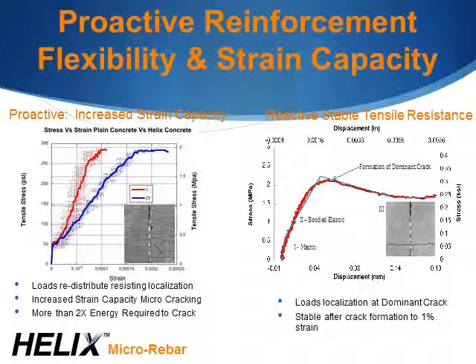At that first part of the curve, which we call the proactive part of the curve, we actually get a very interesting behavior that we are not aware is possible with any type of reinforcement on the market presently. If you look at the two curves there, the red curve is plain concrete and the blue curve is Helix-reinforced concrete with 15 kilograms per cubic meter, or 25 pounds per yard, of Helix. What we see there is a statistically significant reduction in the modulus of elasticity and increase in the strain capacity of the concrete.